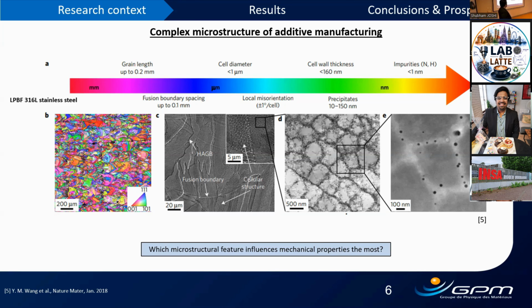Then down the length scale, we have fusion boundaries and cellular structures because of rapid solidification, which is normally associated with the laser powder bed fusion process. Down the scale, we see these dendritic cellular structures in detail, with dislocations entrapped on the walls. And finally, at the lowest scale, in nanometers, we see these second phase particles, or precipitates, or oxides.